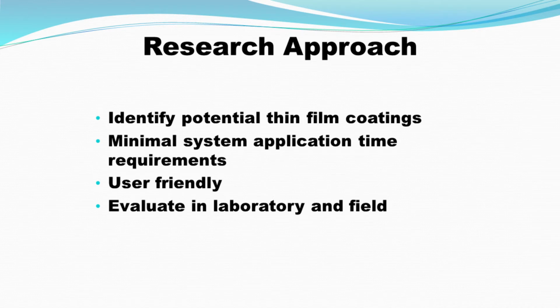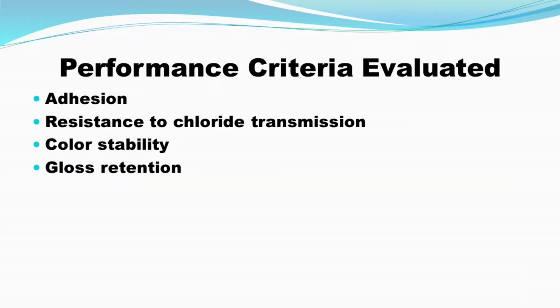The last study that makes up this presentation was looking at better approaches, or at least different products, that would give you a better solution to chloride ion penetration resistance for your concrete. I wanted to identify thin film coatings, coatings that had minimal surface preparation requirements, minimal application time, and that were user-friendly. There was an assumption made that state forces would be the primary ones putting these coating systems on. The criteria for looking at products: obviously we wanted good adhesion to concrete, good resistance to chloride intrusion, and color stability with some gloss retention for the aesthetics component.